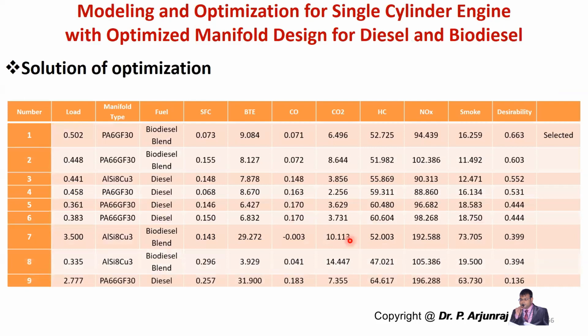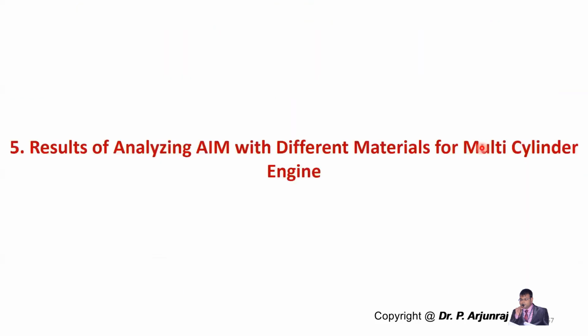And this is the solution for optimization, where we have found that PA6 with glass fiber 30 biodiesel blend is better with respect to SFC, BTE, CO, CO2, HC, NOx, and smoke. Considering all these parameters, we get a higher desirability factor for PA6 with glass fiber 30%.